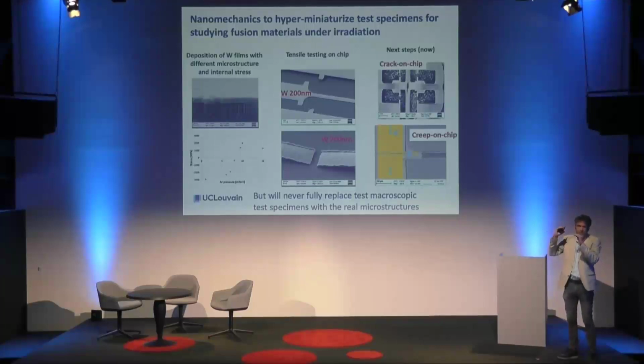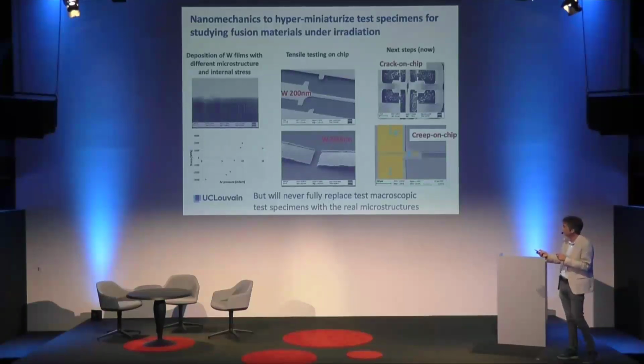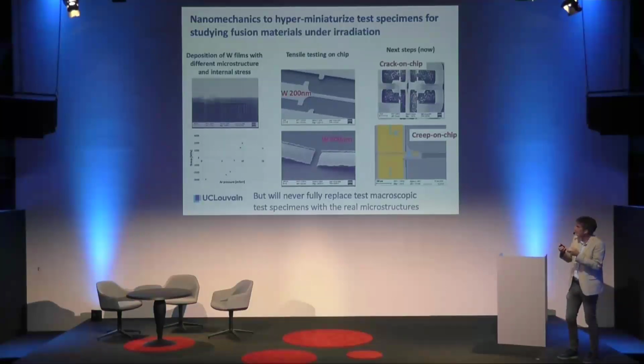They are made by electrodepositions. We are using techniques used in microelectronics to produce microelectronical components, but this time we have adapted these techniques to produce micron-scale tensile test specimens and try to extract the material behavior there, based actually on the deposition stresses, residual stresses, which are used then to pull on these different samples.